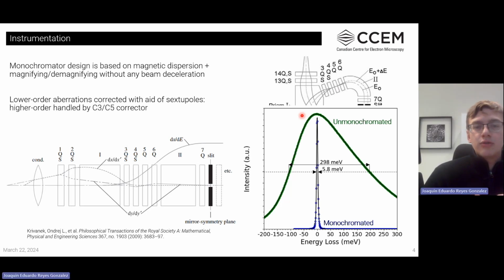If we do a bit further tweaking, we can get this down to that 3.2 that I mentioned earlier. The 5 is pretty much the easy baseline that we go for, but you can get it a bit further if you really want to try and push it. You just need to really lower the amount of current that you're getting out - that's the one downside.